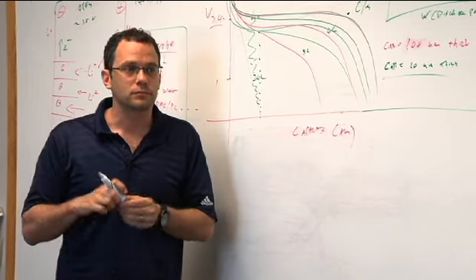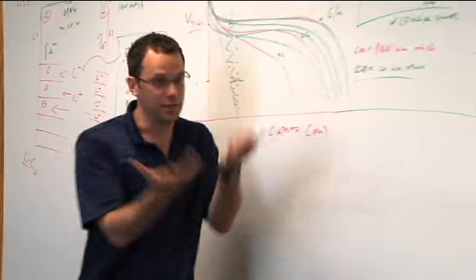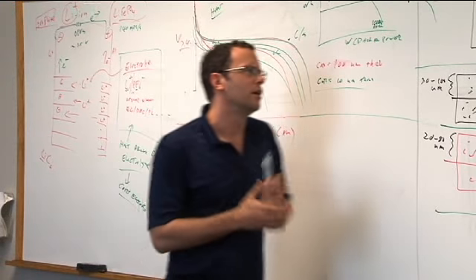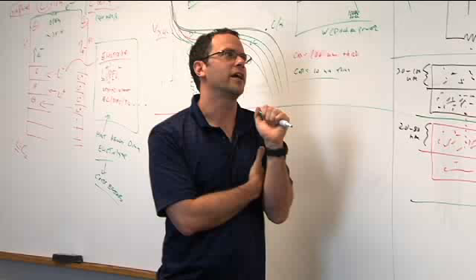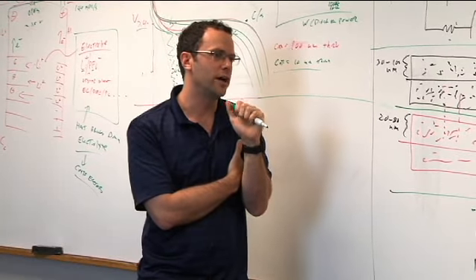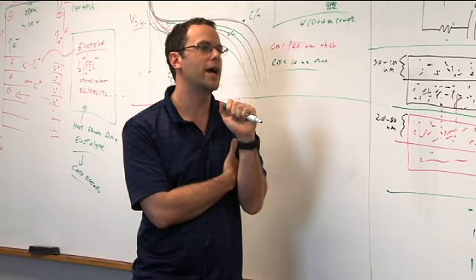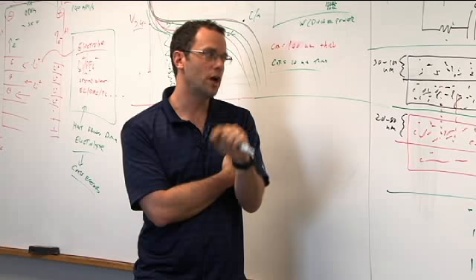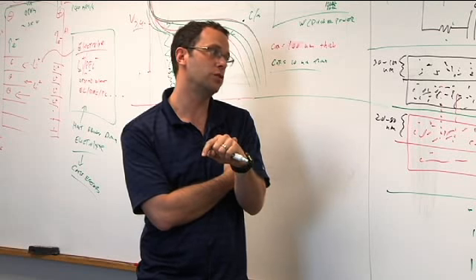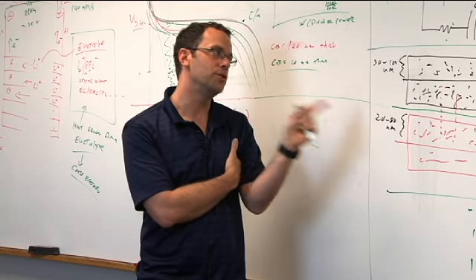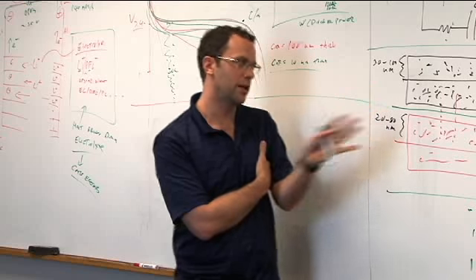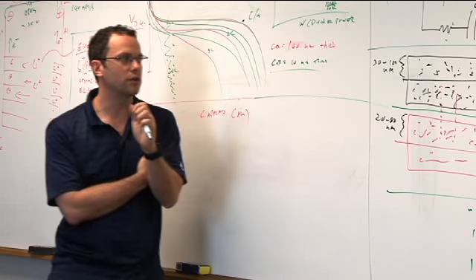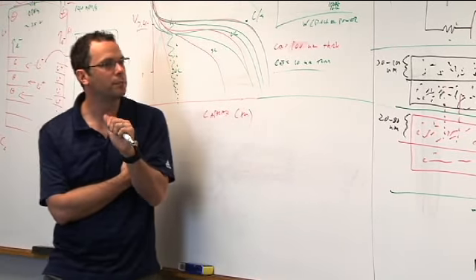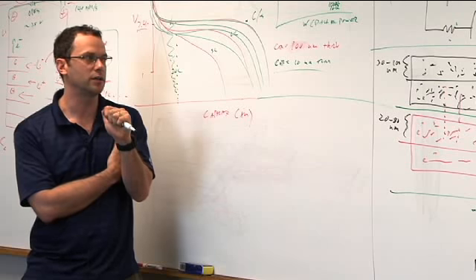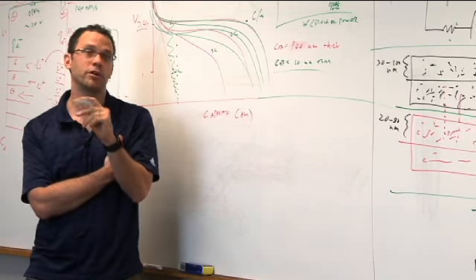How much more efficient? It depends. It's a great question. I would say 20%? No. 50%? It's in like the 5% to 10% or less. You're not going to dramatically increase it. But if charge time, for example, is really important to you, using properly engineered cells you could charge significantly faster by a pulse technique versus a constant current technique. How much faster? 40 or 50% faster.